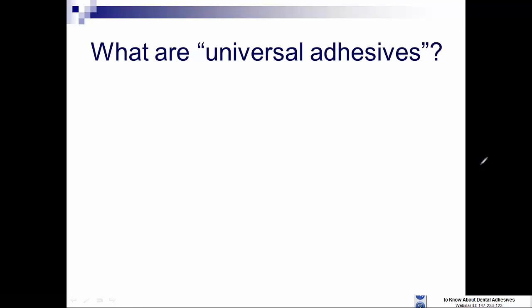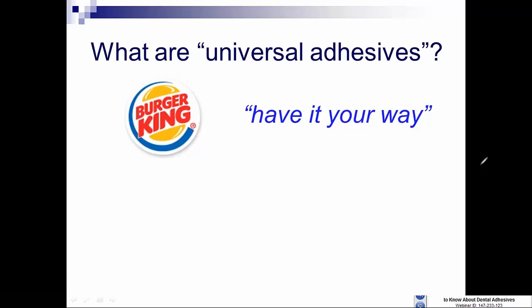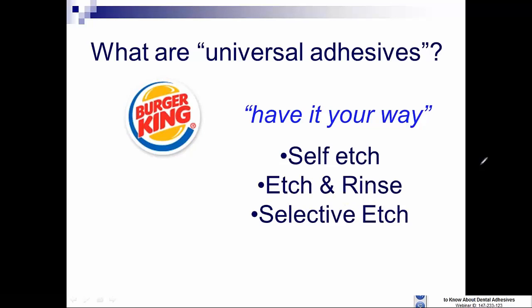And this has led to the creation of now the new state-of-the-art, the so-called universal adhesives, or as I like to say, it's the Burger King method. You can have it your way, doctor, based on your clinical situation. You can use the systems as a self-etching adhesive. The bond strength to dentin is excellent. The bond strength to enamel is the same as other self-etching adhesives, but not equal to what is able to be generated with phosphoric acid. These systems can be used with etch and rinse or total etch, where enamel and dentin is etched, and the dentin bond strength does not drop as a result of the dentin being etched, as can be successful in a self-etching technique. And what is now really the true developing standard of care is the so-called selective etch.